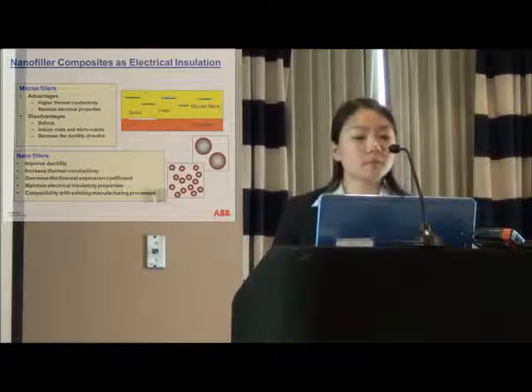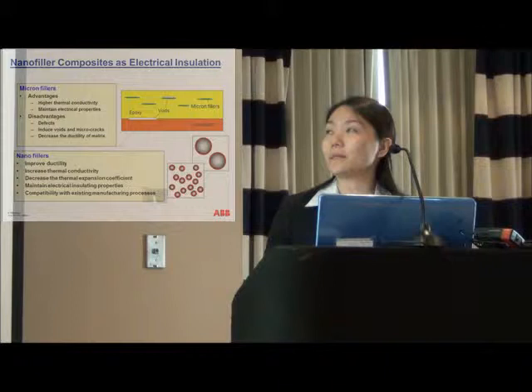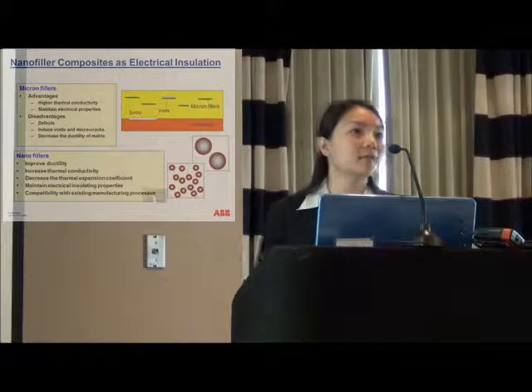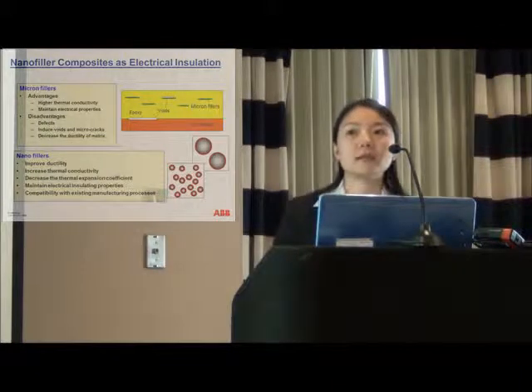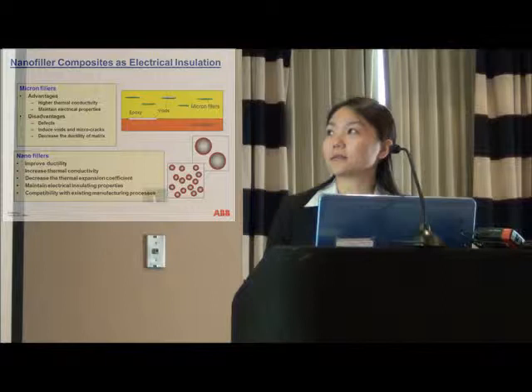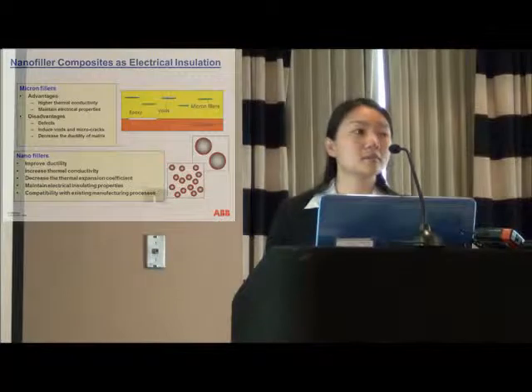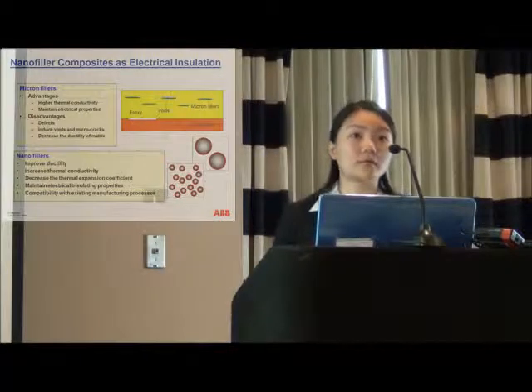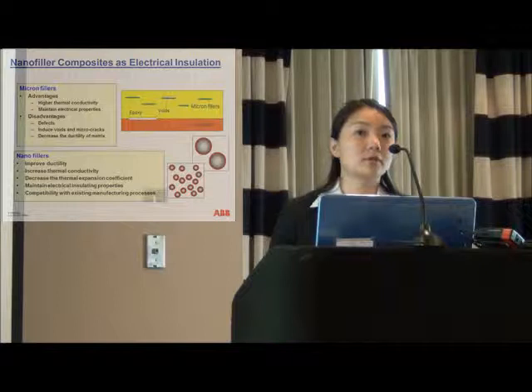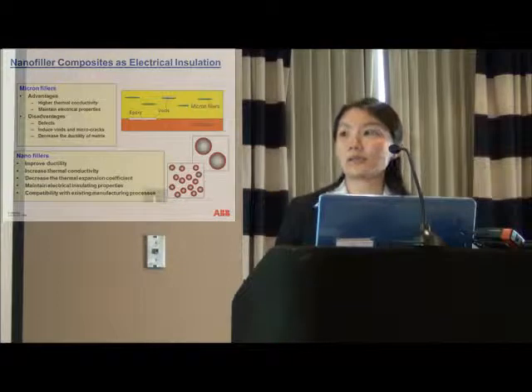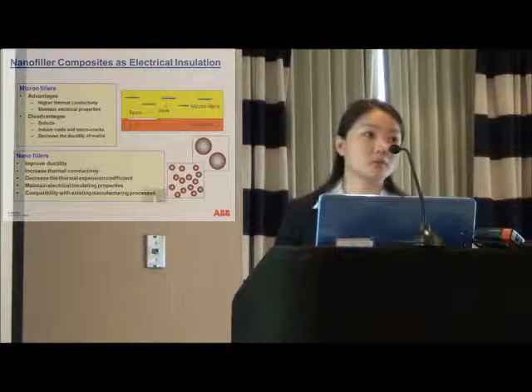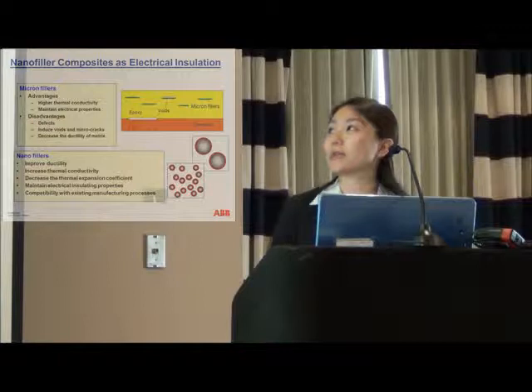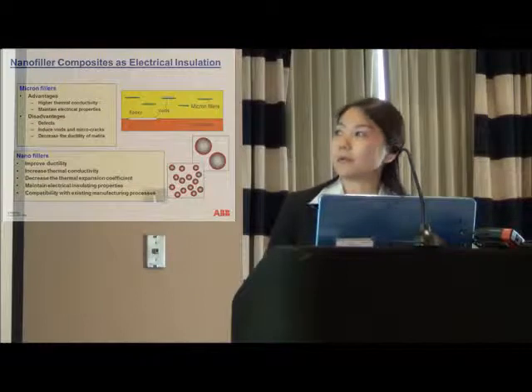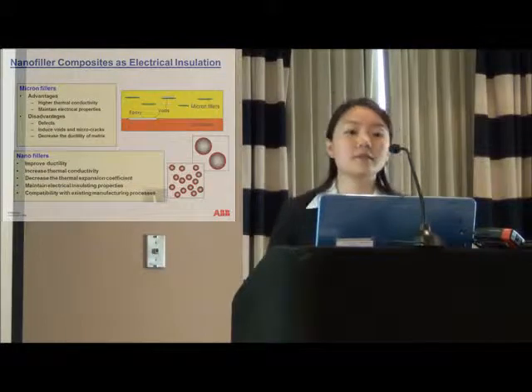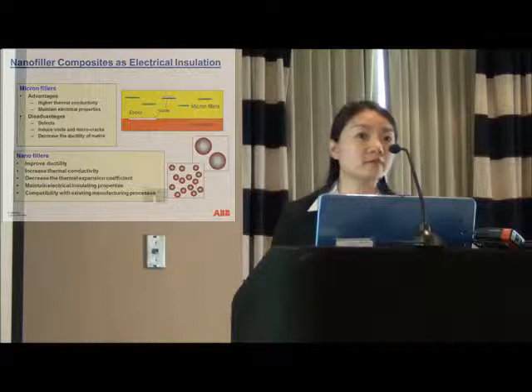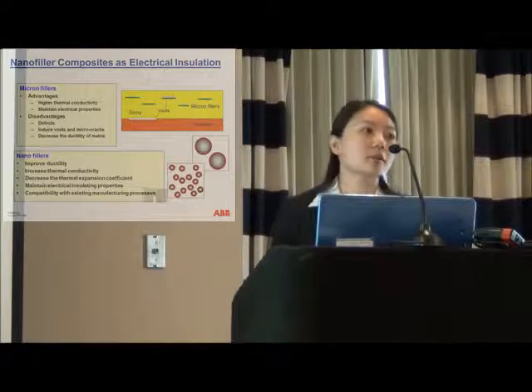But there are some problems with microfillers - they are kind of defects themselves, that they can introduce voids and microcracks to the system, which will decrease the ductility of the epoxy. Epoxy is very brittle, we know, and if the ductility decreases, that is not very good for the long time life of the material. So we are thinking of using nanofillers instead of microfillers, because we know nanoparticles have much higher surface area compared to the micro-sized particles.